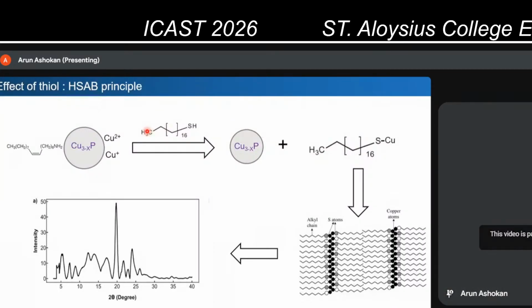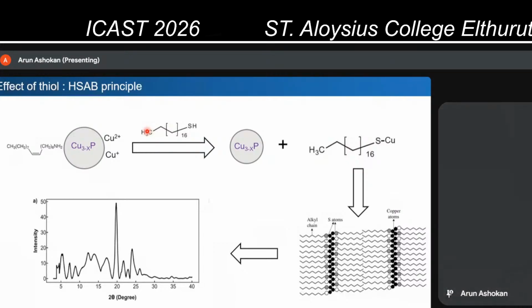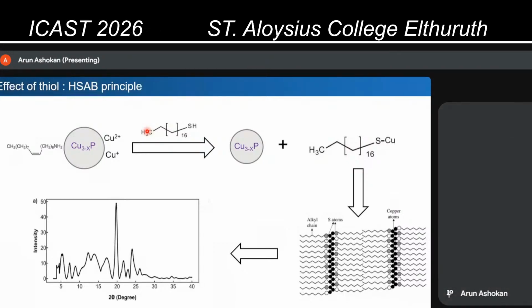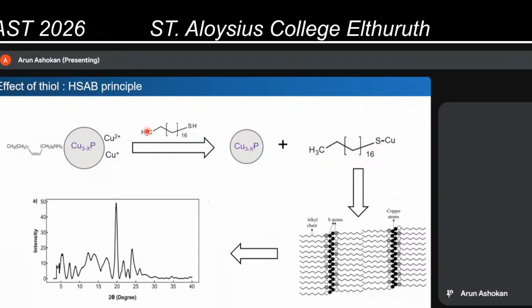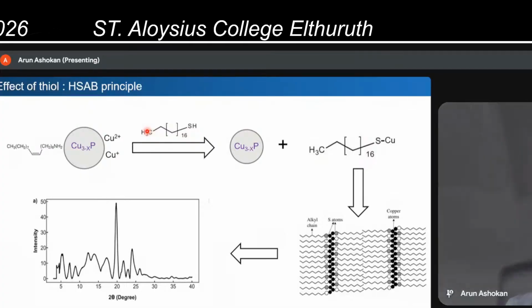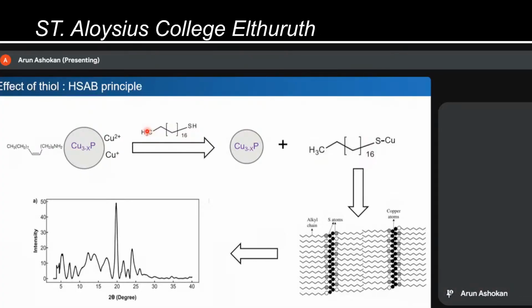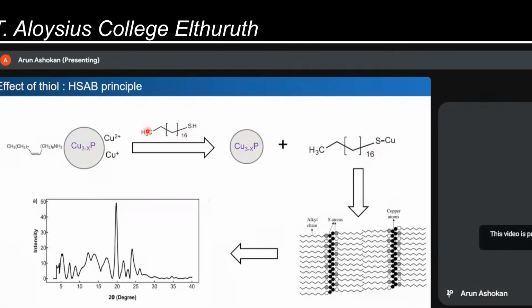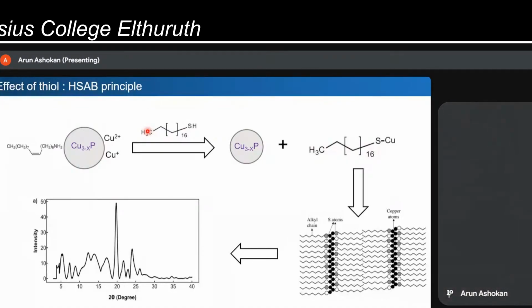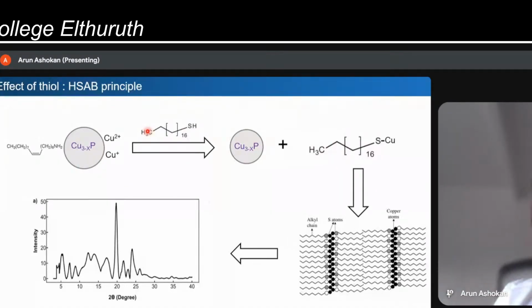So if you use thiol, copper phosphide won't work. It will basically degrade. So care should be taken when you are using thiol with copper phosphide. That's why we tried all these experiments. Anyway, as I said, we will be using electrochemical methods to modulate the plasmon in these materials.